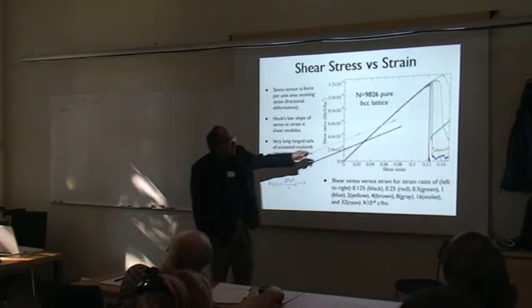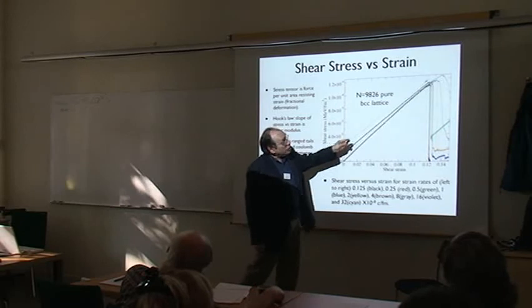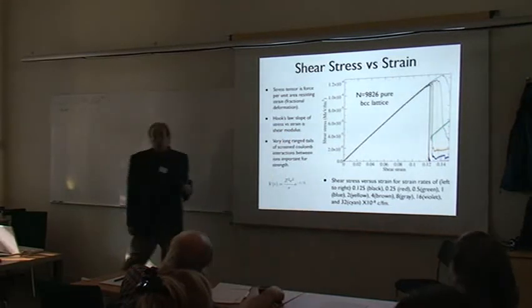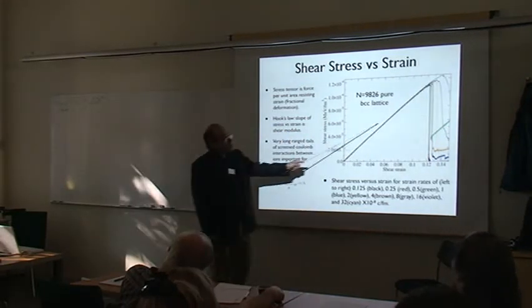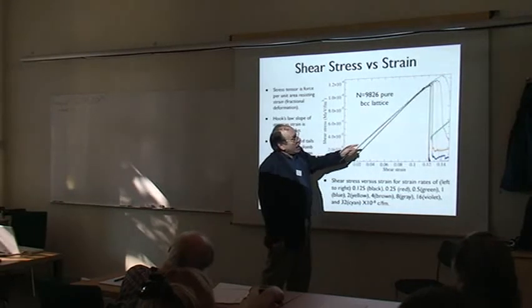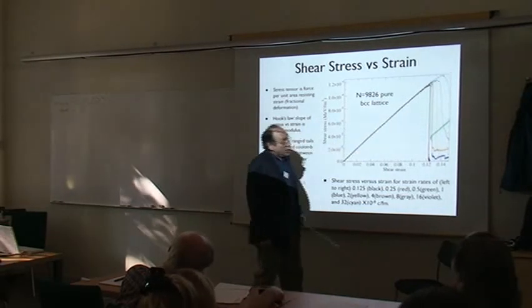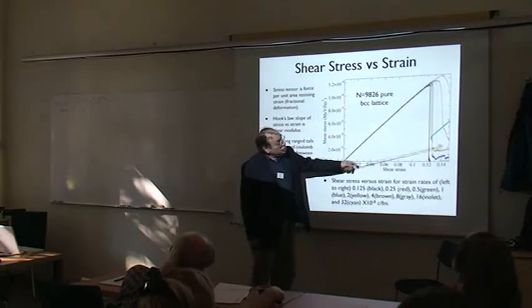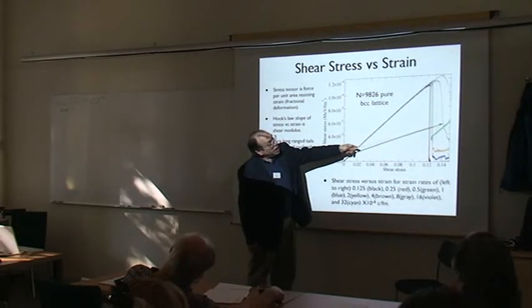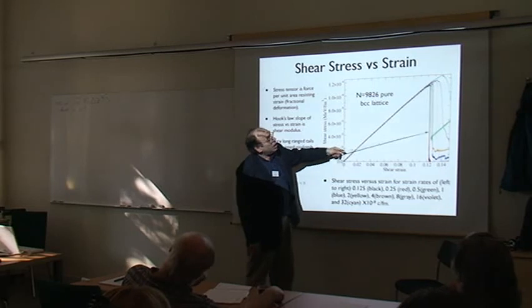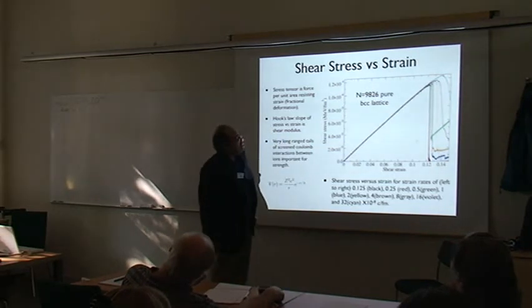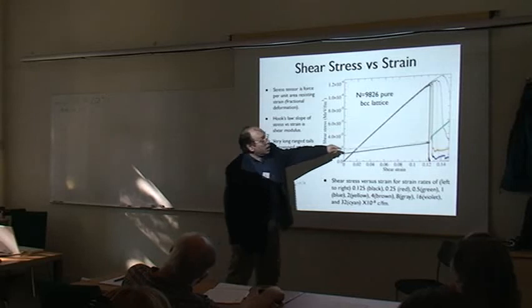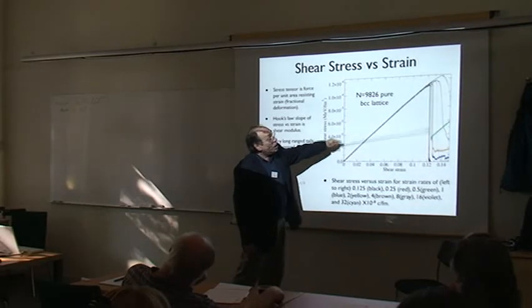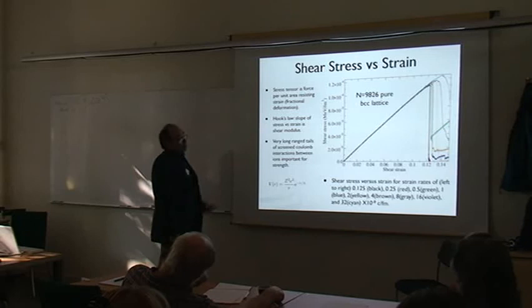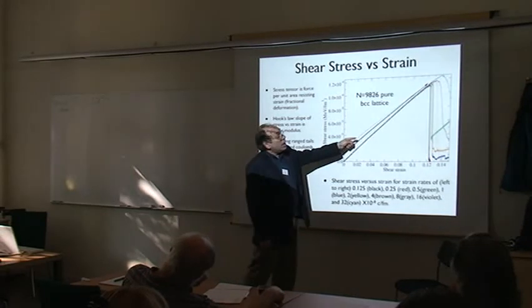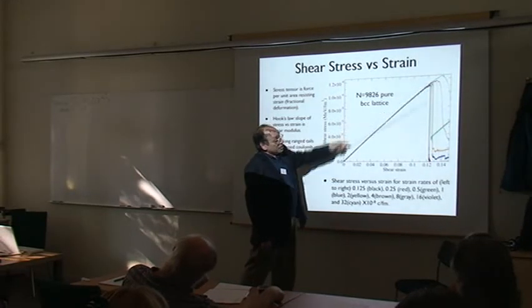And the simulations are for different shear rates. If you deform the system really quickly, it doesn't have enough time to break, and it gets to bigger deformations before it finally fails. If you deform it more slowly, it has time to break earlier, and for very slow deformations, it tends to converge, and you get a remarkably simple curve.